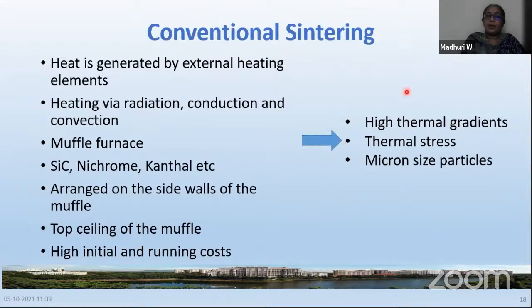So not only this, there are a lot of other disadvantages, like long time. In a conventional sintering, usually the program time would be of the order of 12 to 16 hours or even more at times. Fine. If you're going for metallic alloys and all, at times you need to sinter them for more than a few days together, 10 to 15 days.